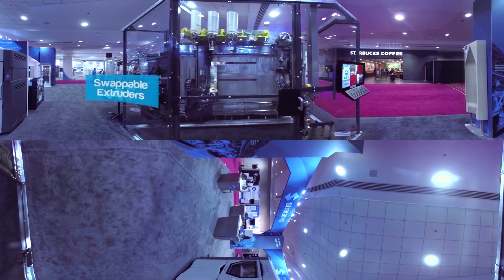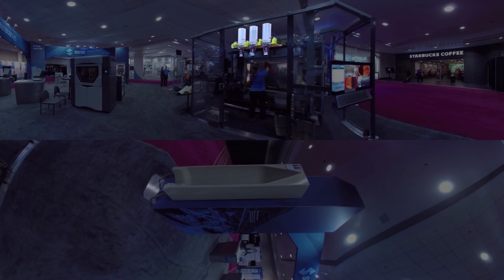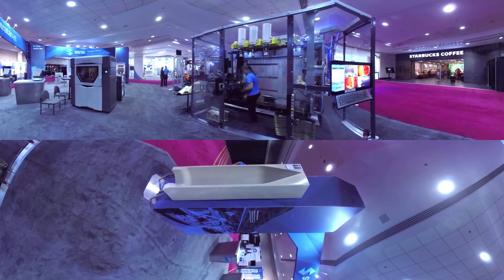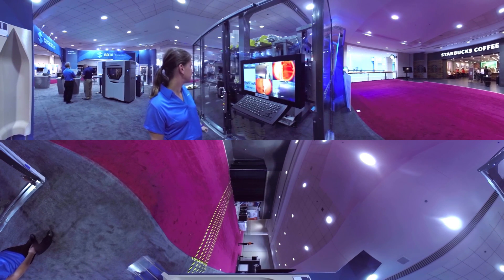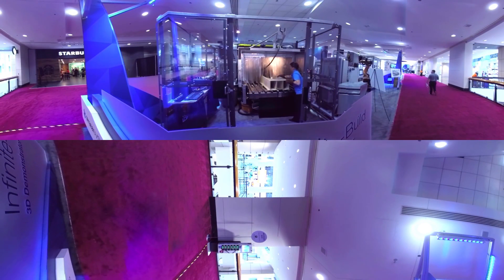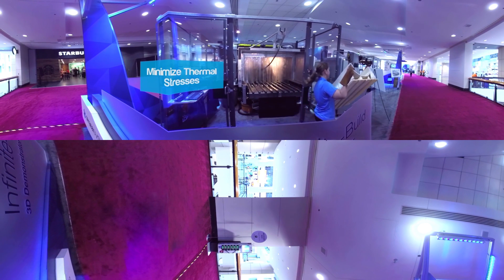The inclusion of an automated tool changing system allows the extruders to be swapped out to accommodate different materials and tool types. If you look at the hoppers on the top, you see 30-pound containers of material which can be automatically replaced, resulting in continuous operation. The interface here shows the part being printed inside the machine. It also provides real-time monitoring capabilities using infrared cameras to monitor the thermal profile of the part and the surrounding environment. Here at the back of the system you can see the part exiting the novel 5-sided oven, capable of creating a controlled thermal gradient to maximize part quality and minimize thermal stresses.